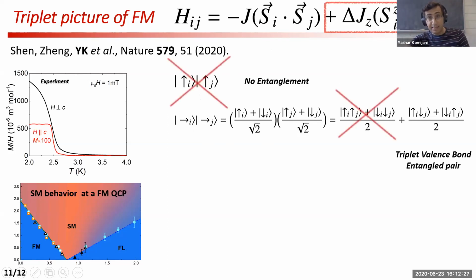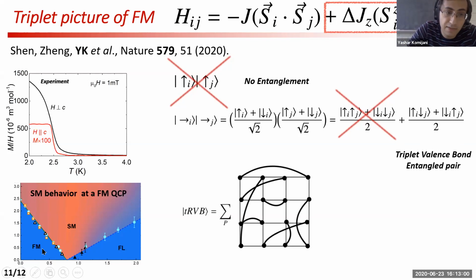Now, if you have some magnetic anisotropy, it turns out that there will be some splitting between the M equal to 0 triplet and M equal to ±1. In other words, these terms are energetically penalized by this term. And we are left over with a projection which leaves us with the M equal to 0 triplet. And this is an entangled state as much as a singlet. So therefore, a correct picture of this ordered phase in the ferromagnet might be that it's not just a product state of the spins, but it might be that it's a superposition of all coverings of triplets. And this is a state which we call the triplet resonating valence bond state.